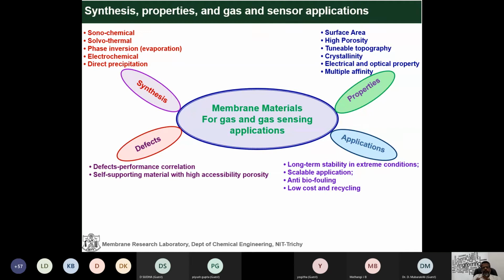Everywhere they are asking, you are making very few materials; is it possible for scalable application? Now, in any kind of technology, you need homogeneous distribution of the inorganic materials. With homogeneous distribution, you ensure that the materials are completely dispersed into the polymer matrix. Then you are able to scale. But leaching is now an issue; leaching is a big issue. So you have to minimize the loading, for example 0.5, a very low loading, the lowest concentration of MOF at high surface area, giving high performance, that is, high property enhancement. That is also useful for anti-fouling properties, low cost, and recycling.